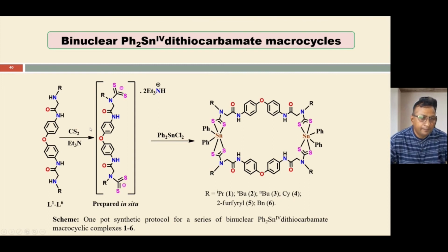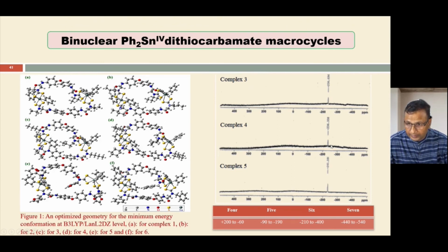So, for example, we have optimized the synthesis of these diamides and used them in the formation of corresponding 1,1-dithiocarbamate ligands, which on interaction with organotin diphenyltin gives us these metallo-macrocyclic compounds in good yields. All the molecules are well characterized, and the tin NMR spectrum clearly suggests the phase purity and the presence of hexa-coordinate tin centers in these molecules. That range of tin NMR signal confirms the presence of hexa-coordinate tin centers.